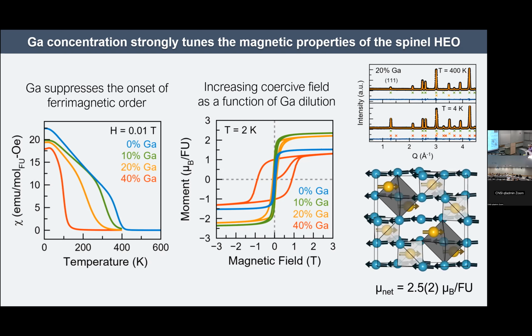Okay, and then just briefly, we've also performed neutron diffraction on the gallium substituted compounds, and the main thing to point out is that this change of behavior here is not explained by a change of the magnetic structure. The material is still ferrimagnetic with the tetrahedral and octahedral sublattices opposing one another. Have you gone to higher fields? No, we have not. We've gone up to 7 Tesla. Are you seeing all the moments, or are you just seeing the net moment? We're seeing the net moment, yeah.